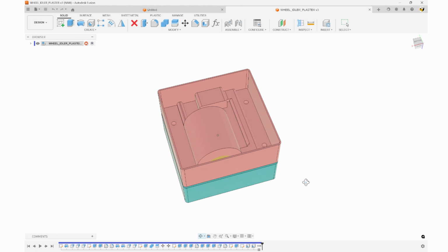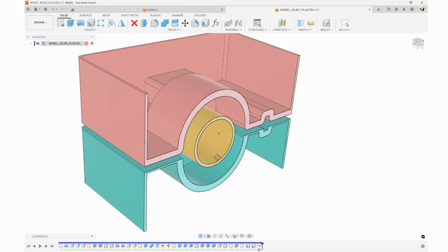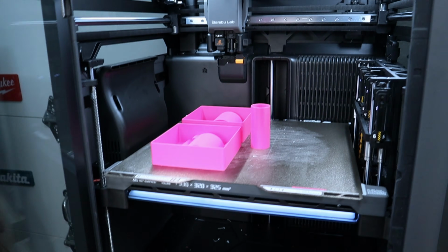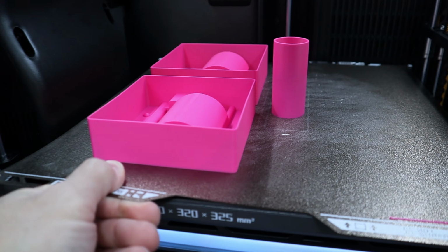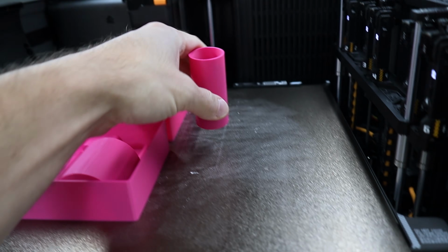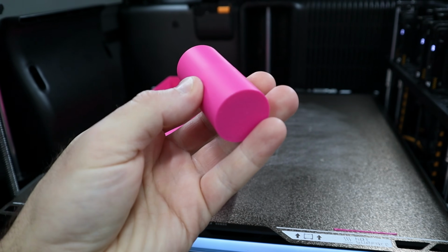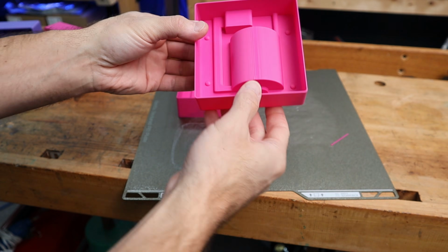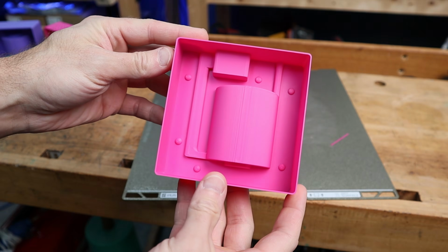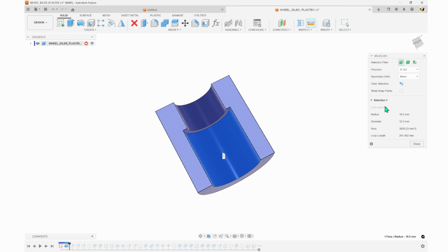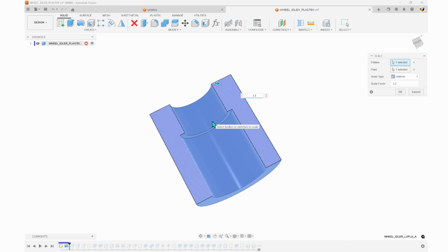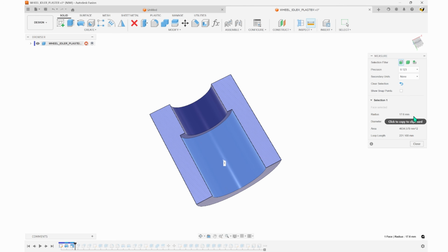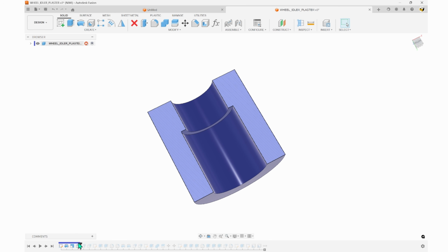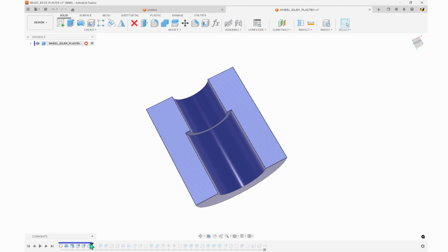For the second method, I've designed a basic positive mold with walls all the way around it in Fusion, printed on my H2C. Now it's important that this mold stays completely flat, so to minimize the chances of warpage, it is printed very light, with minimal walls, minimal tops and bottoms, and as light of an infill as possible. I've oversized our blank to include an allowance for shrinkage and also for machining. Scaling the part up will not work here. We need to offset the internals to be smaller and offset the externals to be larger. We also need to adjust the length too, so we end up with a usable part at the end after everything shrinks and after machining.